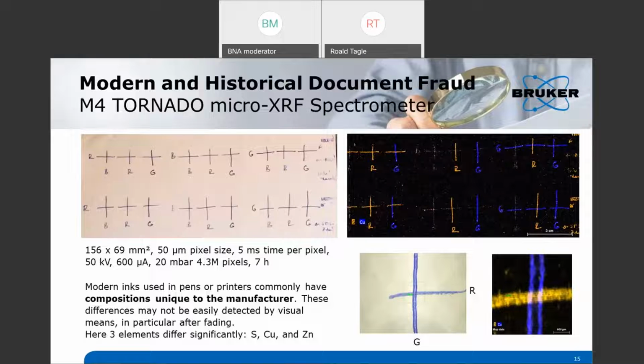It is how the ink and the material interact with the paper, which is useful. For example, here we see very apparently, typical for this material, that when the ink of the gel pen is applied to this paper, we get a distribution of some elements at different distances. That means how deep or how far the different components of the ink migrate into the material.